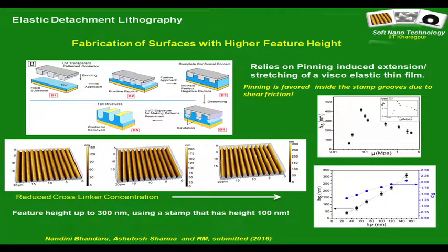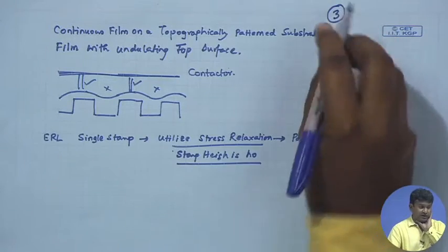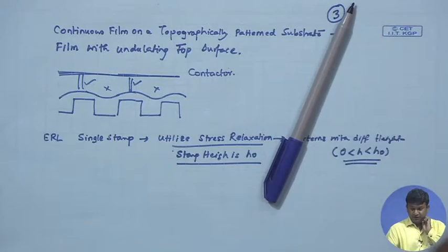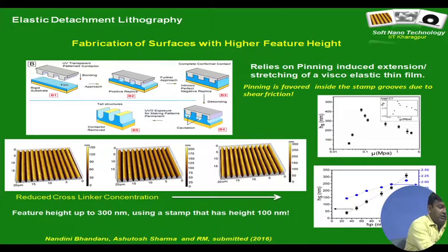And now everybody knows, based on all the concepts of elastic contact instability, that in order to achieve structures at the length scale of each pattern, you need to have a perfectly commensurate structure. So, one chooses the film thickness according to the periodicity of the stamp available. So, this is the whole sequence.